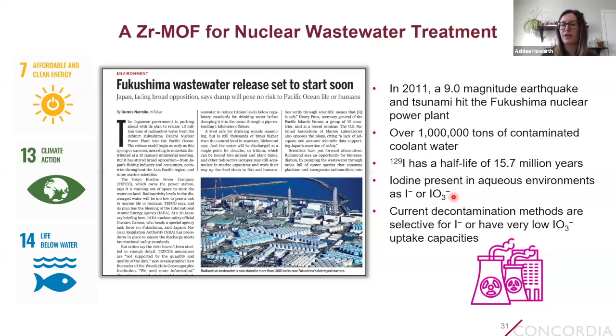And current methods that are used for the decontamination of this type of water, which is particularly ion exchange resins, are selective for the removal of iodide, but they have very low capacities for the removal of iodate or other oxyanions. And so we were interested to see if we could find a zirconium-based MOF that could have a high capacity for the absorption of iodate oxyanions, so we could hopefully work towards cleaning up this water.